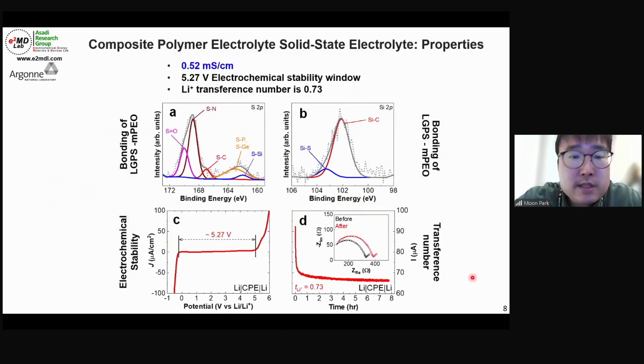So this slide shows the composite polymer electrolyte property. First of all, a very high ionic conductivity was observed, 0.52 millisiemens per centimeter. And also in the high resolution XPS, sulfur 2p and silicon 2p, we saw strong evidence for the bonding between sulfur and silicon, which is silane bonding. The electrochemical stability of 5.27 volts shows a wide window for improved stability of the solid state electrolyte, and also the lithium transfer number was 0.73, which is high and consistent with the great ionic conductivity of this new type of solid state electrolyte.